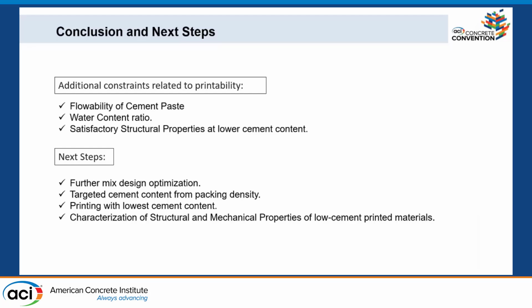By these results, we have come to a conclusion. We need some additional constraints related to printability. We need to maintain the flowability of the cement paste. We need to ensure the water cement content ratio, and we need to satisfactorily maintain the structural properties so that it maintains the mechanical strength after printing the specimens. For the next steps, we are trying to optimize this mix design and maintain our cement content goal with the packing density we have got from the optimization curves as well as the packing density calculation. After that, with that packing density mixture, we are trying to print that material and test its mechanical properties with low cement content.